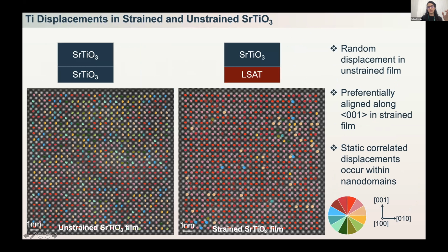Okay, here we go. You're seeing here two representative images of strontium titanate grown on strontium titanate in its unstrained form. Just to mention, the dots that you're seeing are the displacement or polarization vectors, and they are color-coded based on this displacement wheel that you're seeing here. You can see that for the case of unstrained films, domains are forming, but on a very small length scale. However, as soon as we strain this film, the domains form on a larger length scale. And as you can see, displacements are preferential along the 001 direction.